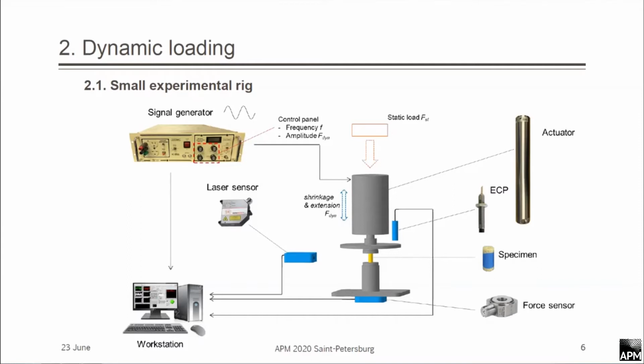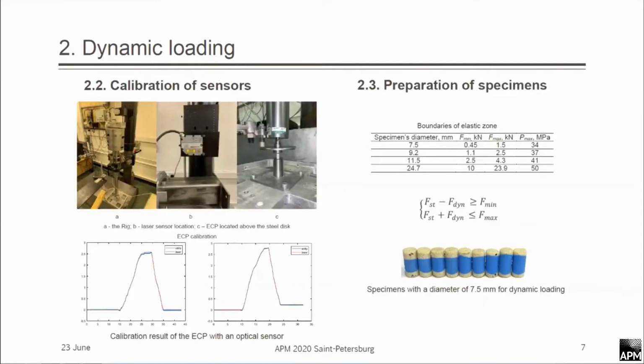The sensors were calibrated here, and on the bottom you can see a perfect match of one sensor calibrated against another with more resolution. Then, in order to stay in the elastic zone, and due to the restriction of load applied by the actuator, which was 1 kilonewton, we had to use the smallest possible sample in diameter. So 7.5 millimeter samples were produced at the beginning, as I mentioned for one of the sizes. So we had to be in these conditions.